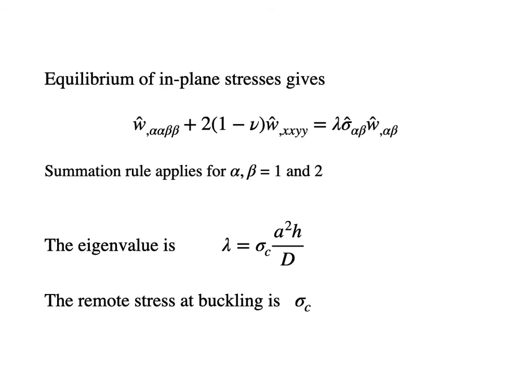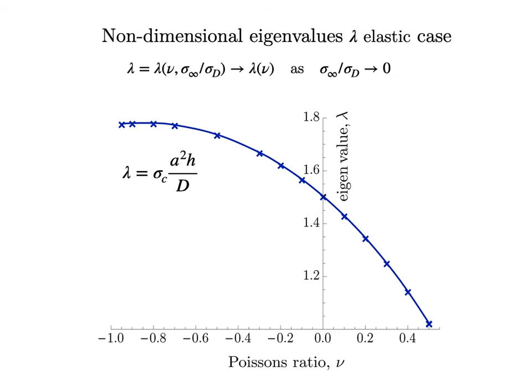The eigenvalue is given in the next equation. The lambda is equal to the critical stress for buckling, crack length squared, and the thickness of the foil, and D is the plate stiffness. As you see on the top of this slide, lambda is a function of Poisson's ratio and the ratio of nominal stress to cohesive stress. Lambda approaches a function only of Poisson's ratio if the nominal stress is small. And this is what this case is.